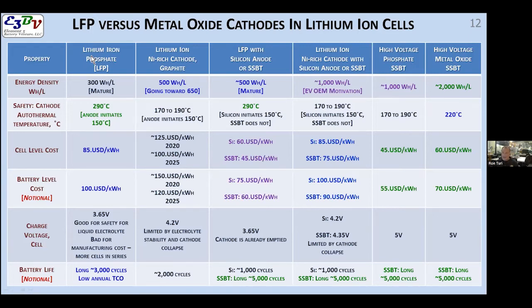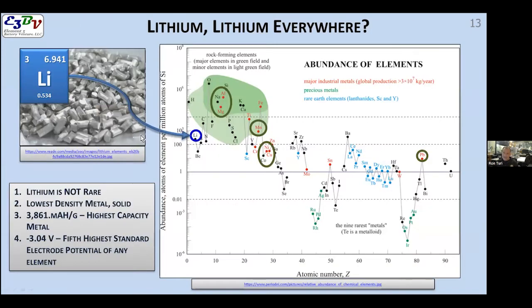Use the Faraday constant to calculate the milliamp hours per gram. And when you make cells, you talk about watt hours. You really don't talk about it until you make the cell. So this would assume it's against, for example, a graphite anode. So there are a lot of implicit things here as well. But you get a general idea of what the trade-offs are by looking at this kind of a curve, this kind of a graph.